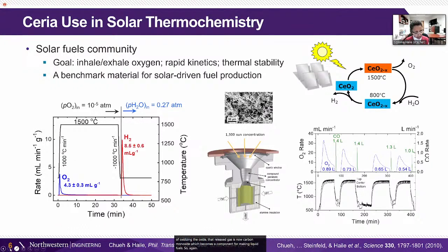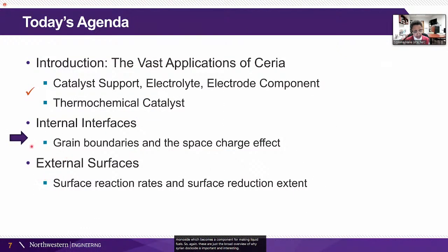So again, these are just the broad overviews of why cerium dioxide is important and interesting. So let me dive now into some of the science of what we've done here beyond the broad application sides. One of the things that's very important is the fact that in this particular material, the internal interfaces, the grain boundaries, are quite resistive. And that becomes a real challenge if you want to decrease the operating temperature of the fuel cell. So let me jump into that.